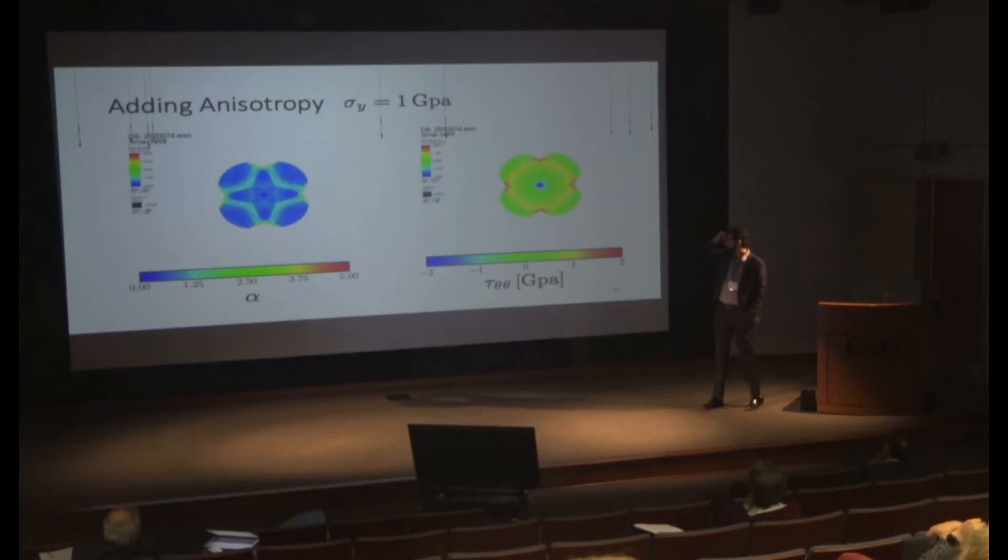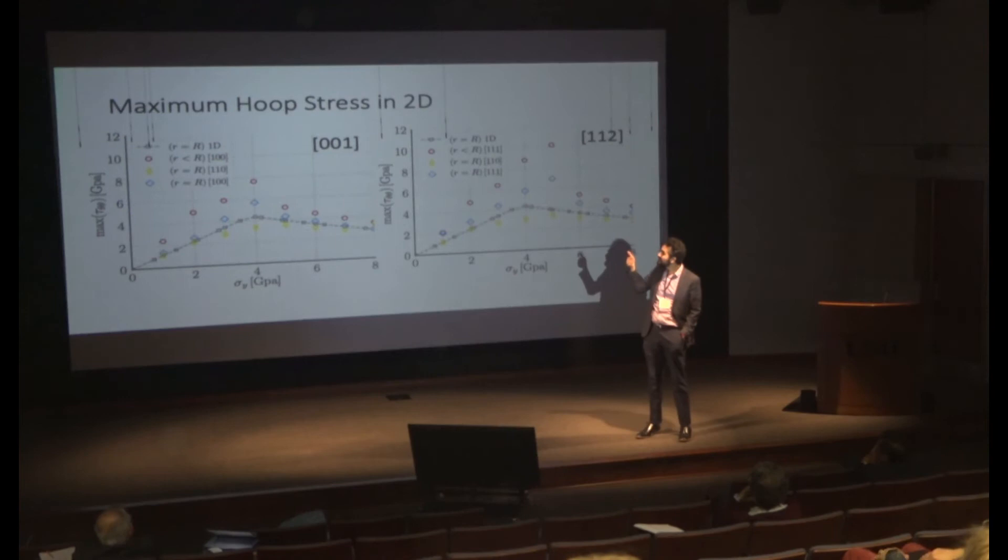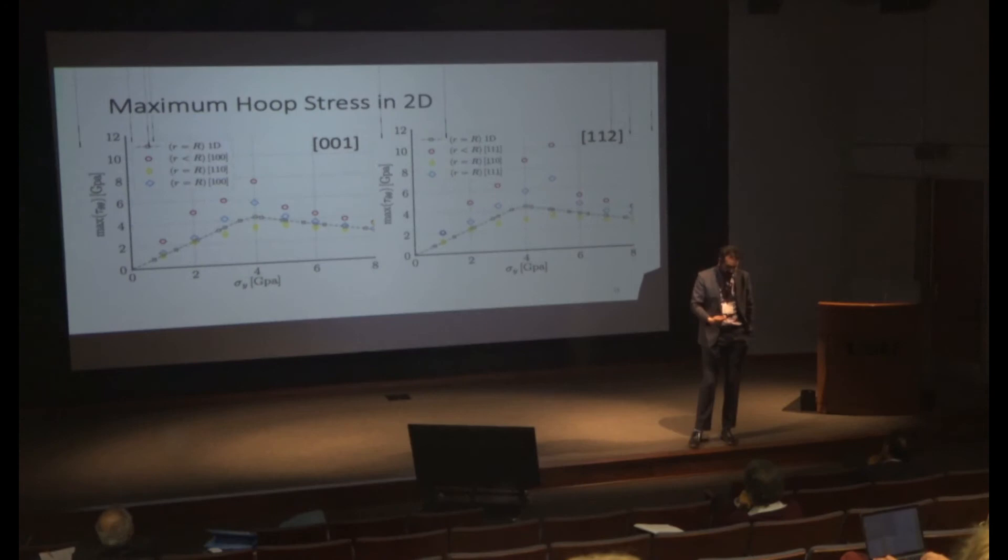What is the consequence of that? You get a lot more bang for your buck. Because of that localization, when you have localization you have larger amounts of that tensile eigen plastic strain that you created on the surface, which helps you create tensile stresses.